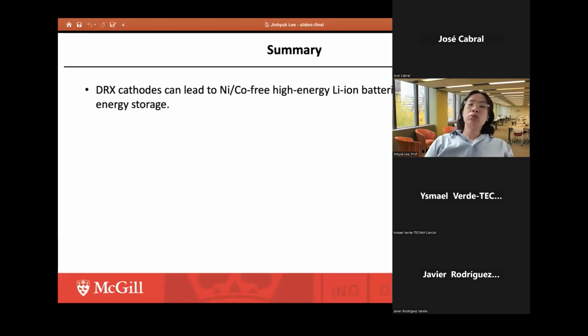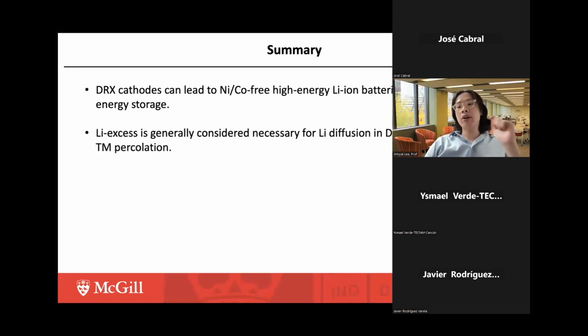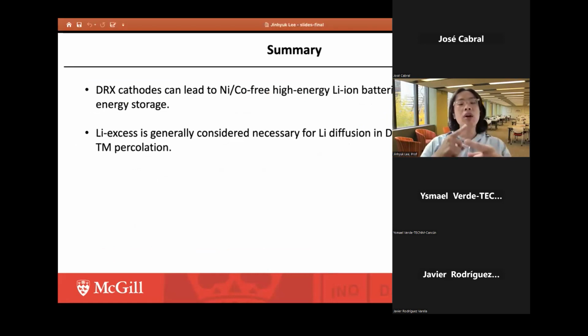So today I would like to show you that the DRX cathode can lead to nickel- and cobalt-free high-energy lithium-ion batteries for sustainable energy storage with higher energy density and lower cost. And the key idea is that the lithium excess composition is critical for lithium diffusion in the DRX structure by introducing so-called zero-TM percolation.